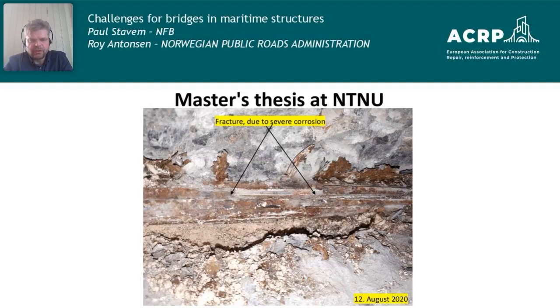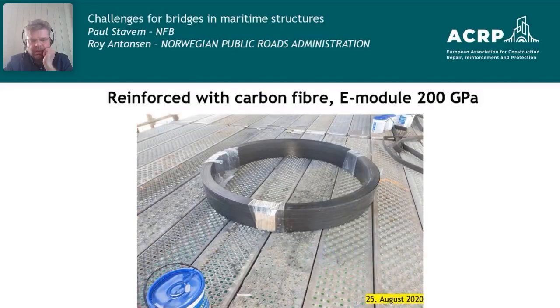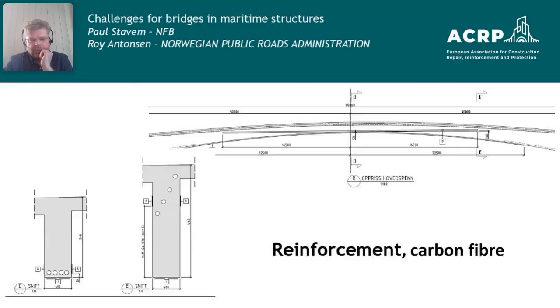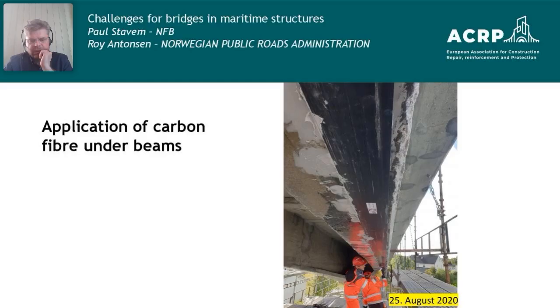But because of the corrosion, here you can also see we found later the corrosion cracks, or actually the threads have been totally corroded away. These are scary photos, but still we were within the safety margin of the bridge. We decided anyway to strengthen it. So here are the carbon fibers that were applied, and for those interested, you can see the details on the design of the strengthening systems. I will just show you how we applied the carbon fibers under the beams here. It was glued on with epoxy. So this is a safety precaution for the remaining 3 years of the bridge, but Nordland County still has to build a new bridge here because of the ongoing corrosion in the main carrying system of the bridge.